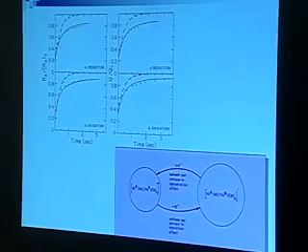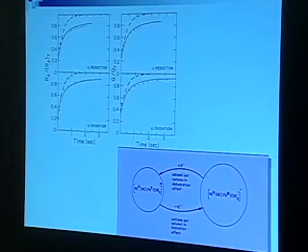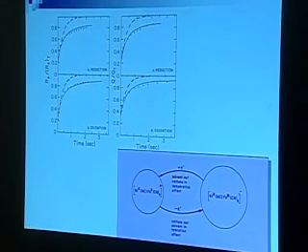So let me just tell you where this is going to go. We have this water problem. And so to start to try and get a handle on this water problem, we switch from cyclic voltammetry to chronoamperometry, actually chronocoulometry. And we do it two ways. We do standard chronocoulometry. That's this scale over here, or set of data, I should say. And we do spectral electrochemistry. We're using our ability to monitor the diffuse reflectance of the surface of the electrode to see if we have iron 2 or iron 3 there, and follow that as a function of time.